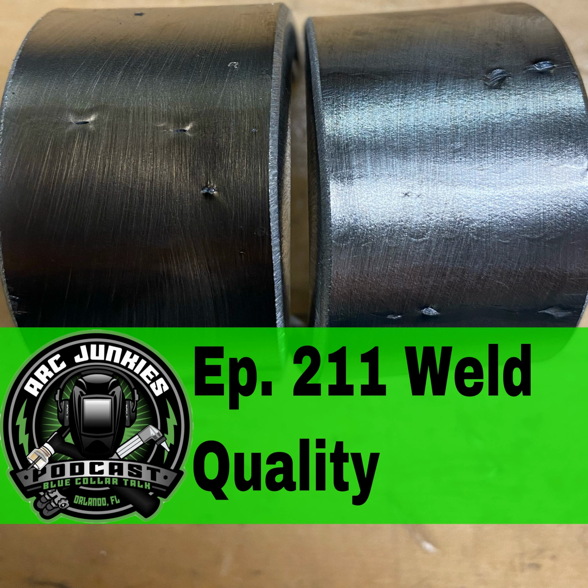Another thing that can cause it is a travel speed that's too slow. So if I'm traveling too slow on this piece, my weld metal or my puddle is getting too big and it's not reaching the back side of that material. I'm putting too much weld metal in there and it's kind of getting stuck. So think of a funnel that's getting clogged. I'm not quite reaching the back side of that material.